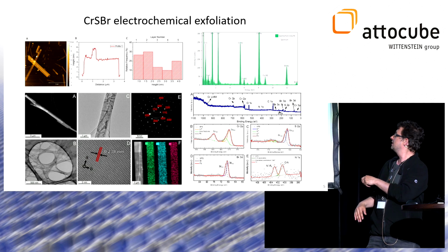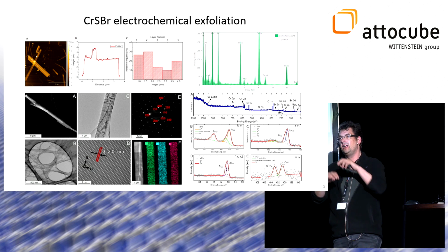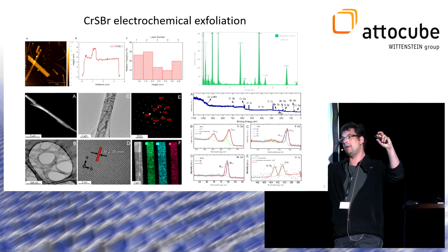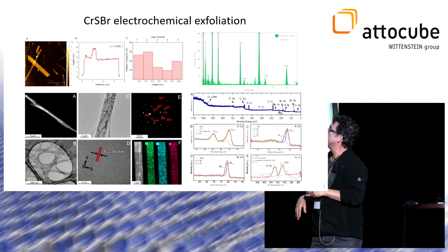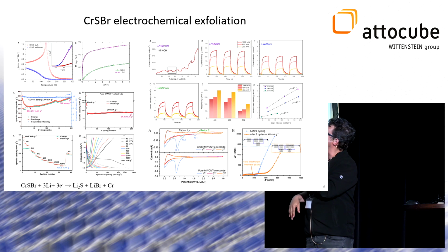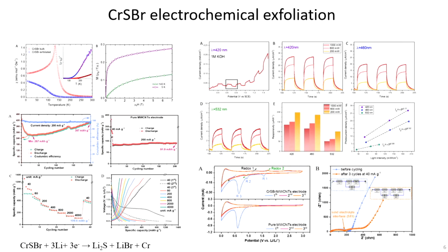You can find this amine peak on XPS, which means that inside the layer you still have the layers of amine. So even this quasi-bulk multi-layer material behaves as a monolayer, which can be seen from the magnetization data, where after intercalation we are switching from antiferromagnetic material to ferromagnetic material because it behaves as a monolayer, completely decoupled.